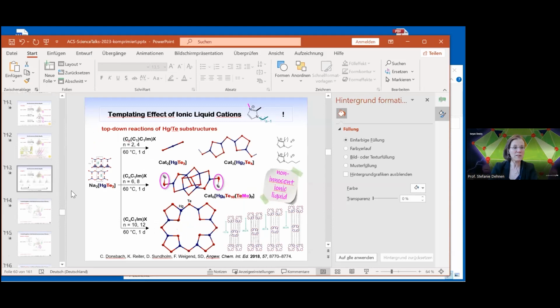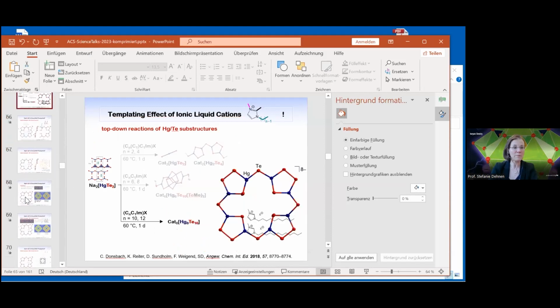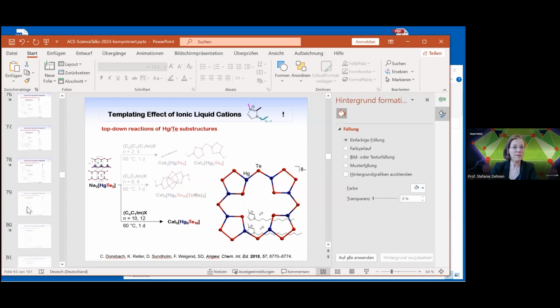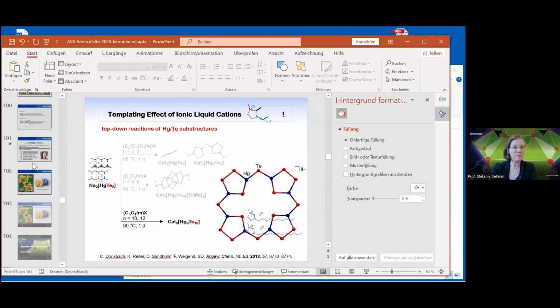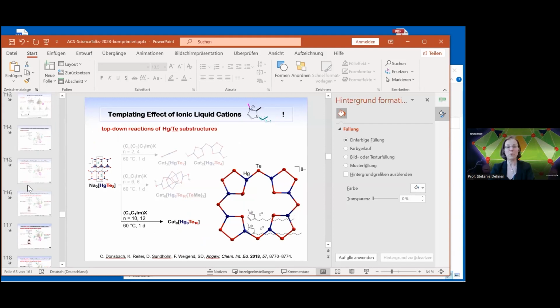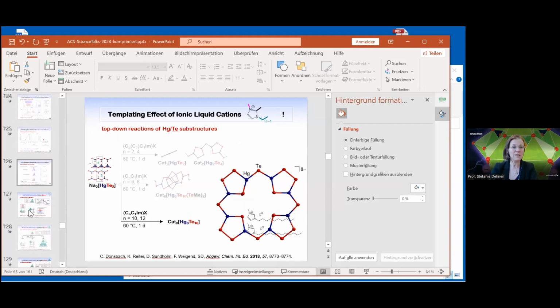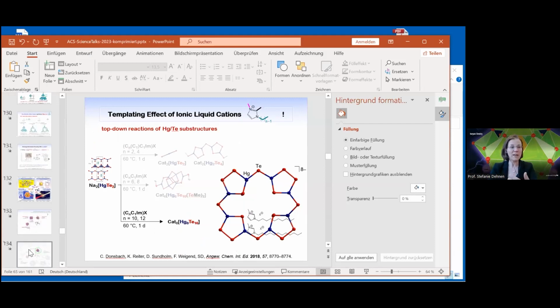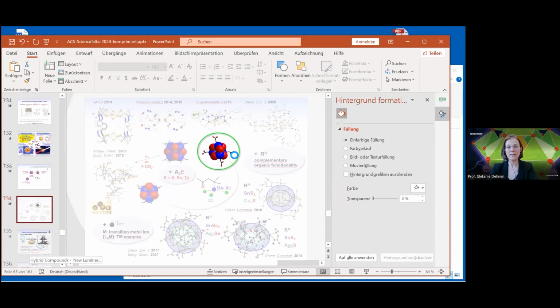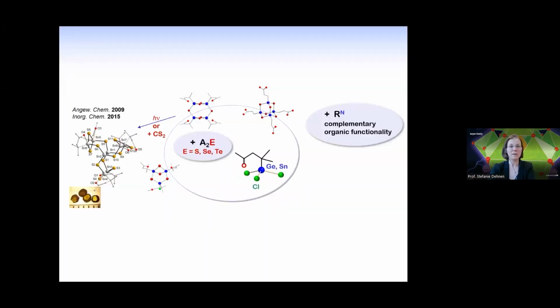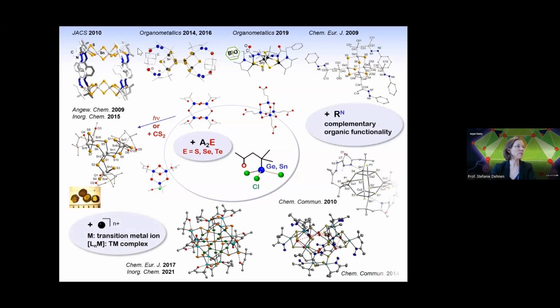In the chemistry with the organoelement precursors, this is somewhere here, we could show that it's possible to react them with metal atoms, for example, and then form coordination compounds that include these clusters, and then have a framework of cluster molecules and these metal atoms. Here you can see that these clusters can be formed with carboxylic groups. And then just imagine that there is a metal atom here at this place. Then you have the next cluster continuing. And this has been done, for example, with this type of cluster molecules and manganese.